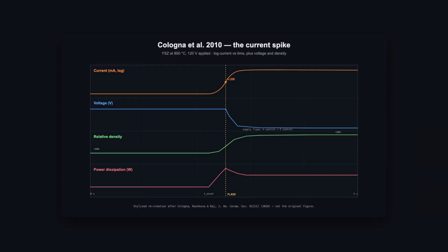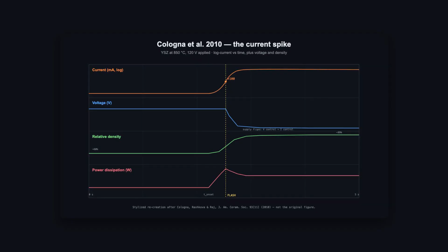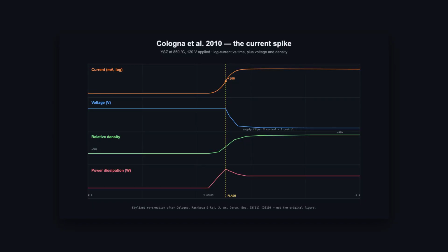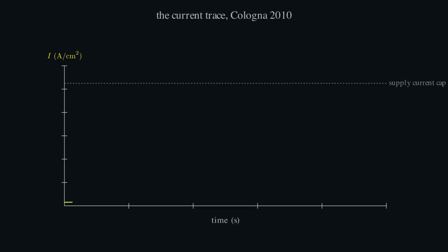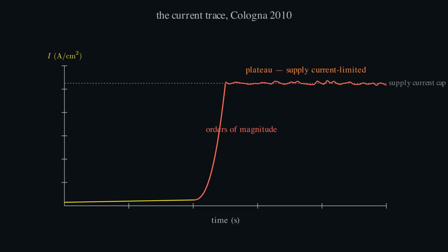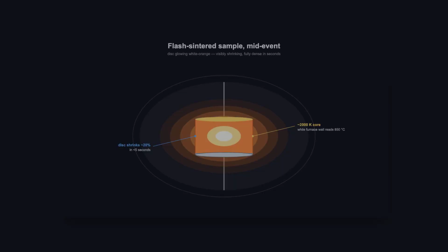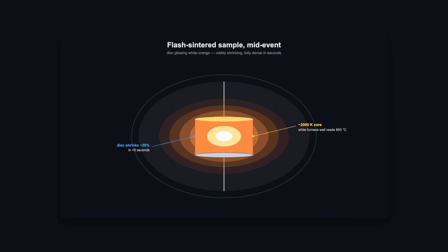And the current did something it had never done before. It spiked. Not by 20%, by orders of magnitude. The supply nearly tripped. Inside the furnace, the disk lit up, orange, white, visibly shrinking. 5 seconds later, the trace plateaued, the glow steadied. When they pulled the sample out, it was fully dense, 99% mirror gray. At 850 degrees, in under 5 seconds.